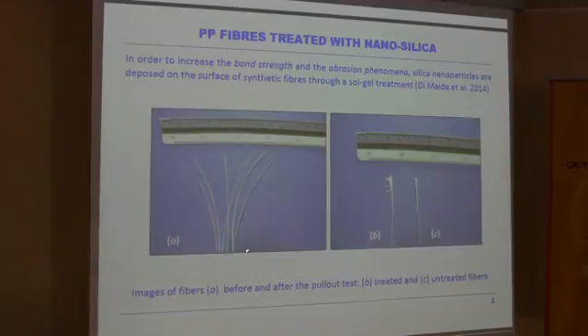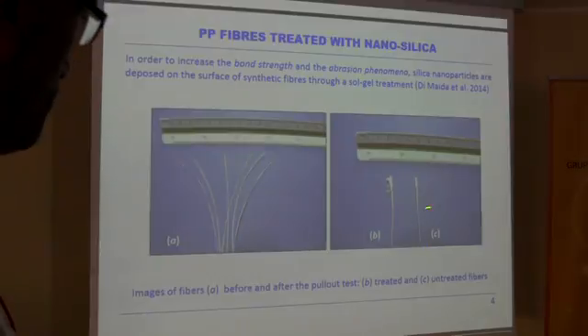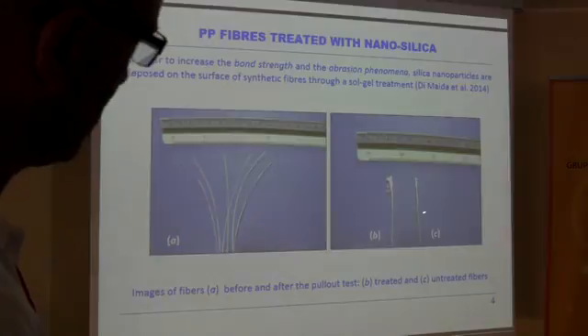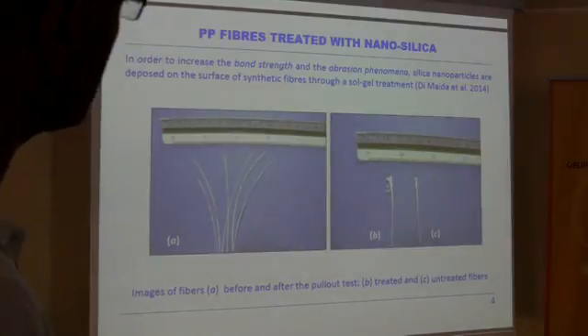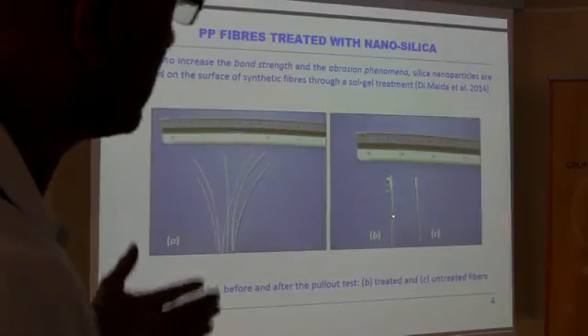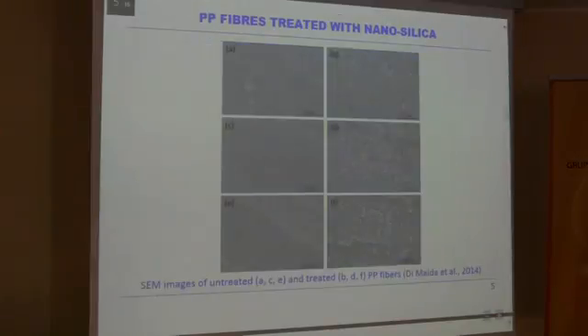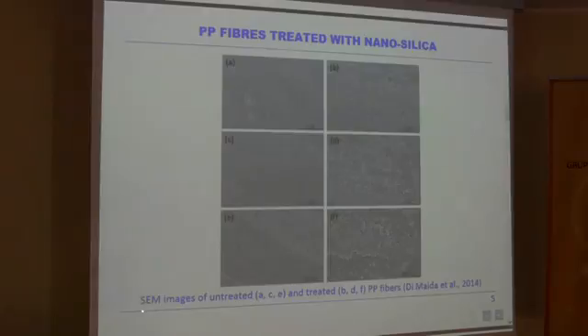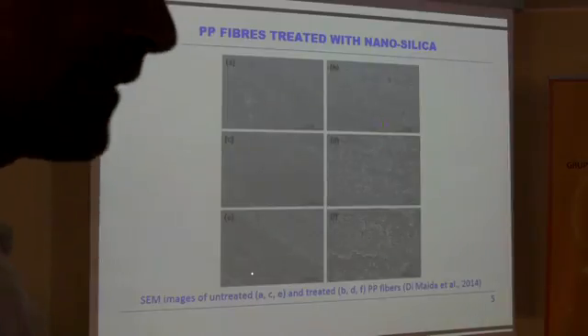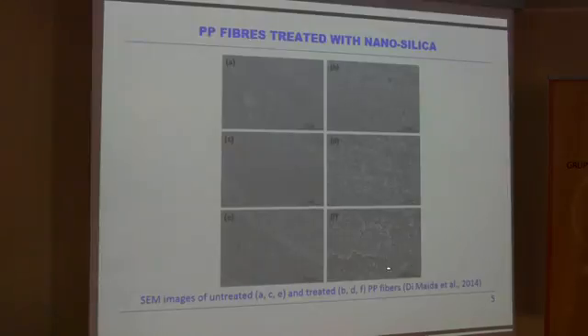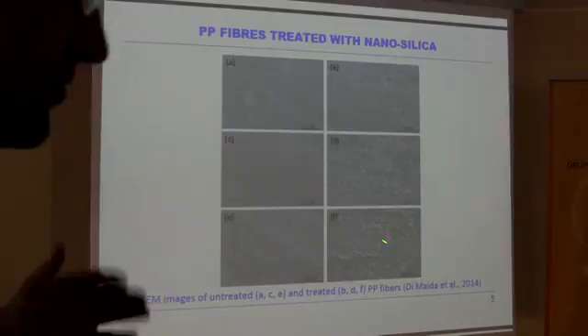Here we have some images of polymeric fiber before the pull-out test and after the pull-out test. This one is for untreated fibers and the other is for treated fiber. As we can see, the treated fiber displays a much deeper abrasion phenomenon. Moreover, there are some SEM images of the surface of treated fibers and untreated fibers. We can see that at the half micron, therefore at nanoscale, the surface displays a kind of rough surface and some kind of islands of silica, nanosilica particles.